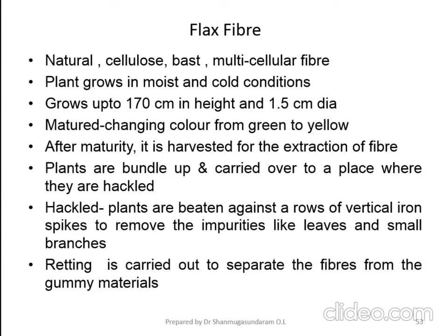Harvesting may be done when flowering is almost over and the stalk is green. The fruit has set, the seed pods have ripened, and the stalk is yellowish brown. Early harvesting gives poor yield with soft fiber. Late harvesting gives a coarser fiber with higher yield. So harvesting will be better when the seed pods have ripened.